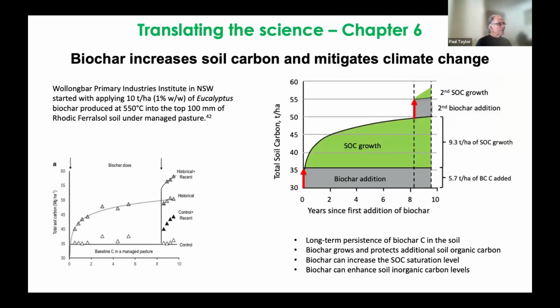Another section in this chapter is looking at the effect of biochar on soil carbon and climate change mitigation. This is a Wollongbar 10-year study. They added 10 tons per hectare of biochar, which is 1%, eucalyptus biochar, produced at 550 degrees, in the top 100 millimeters. And then they measured the carbon in the top 75 millimeters. And these are the results. So we've translated that into this diagram here. Here's the biochar addition. This is the carbon in the biochar. It was 5.7 tons per hectare of biochar carbon, as opposed to biochar itself, in the top 75 millimeters.